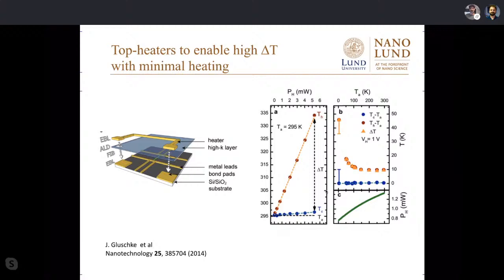And that allows us, so here, sort of characterization experiments. The first one is done at room temperature, where we were able to measure the temperature on the hot side and the cold side of the nanowire as a function of heating power. And you can see the hot side really gets hotter, starting from room temperature, the cold side hardly. And this gets even better if you go to low temperature, because then you reduce electron-phonon coupling, and the phonons as a heat gradient mediator sort of go away gradually. And it turns out at low temperature, you can really, to a very good degree, heat the hot side of a nanowire, and a micron or so, or even just a few hundred nanometers away, it stays cold, which then is a prerequisite to be able to do a heat gradient at low temperature.